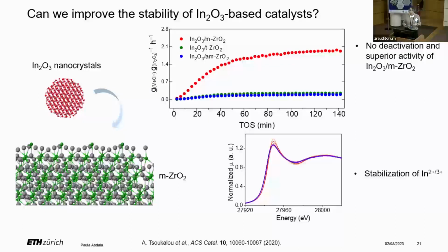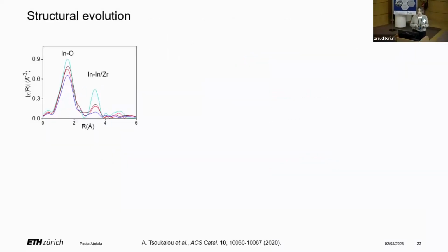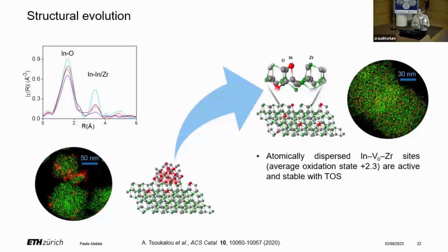But why? Well, when we look at the operando XANES data again, we see that indeed there is a stabilization of the oxidation state as we proposed. So indeed, the zirconia stabilizes it. What about the geometric structure? Here, the EXAFS gave us interesting information. The indium-oxygen sphere decreased slightly. This is possibly oxygen vacancies, but the second coordination sphere decreased more abruptly. And by EXAFS modeling and by a complementary technique, we find out that the initial nanocrystals of indium oxide are dispersed and incorporated into the structure of monoclinic zirconia, leading to highly dispersed indium sites, which are more stable and also more reactive.